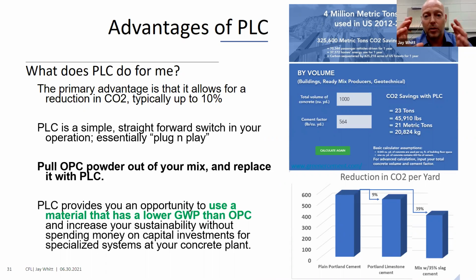You can also look at it from a little micro point of view down lower in the graph there. By simply implementing a type 1L, we will save 9% on CO2 reduction. But also, if you implement an SCM like slag or fly ash, we can reduce that down to even 39%.